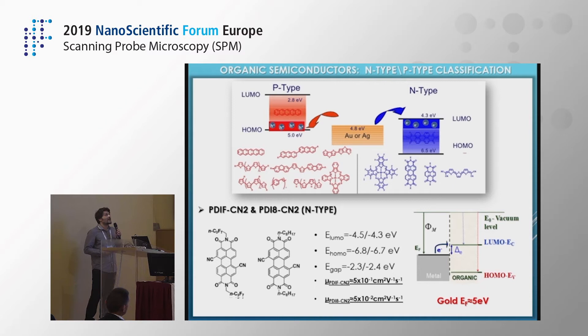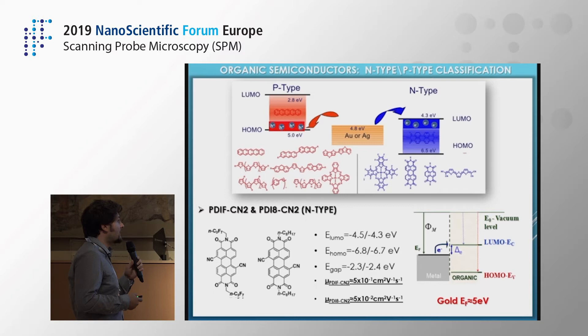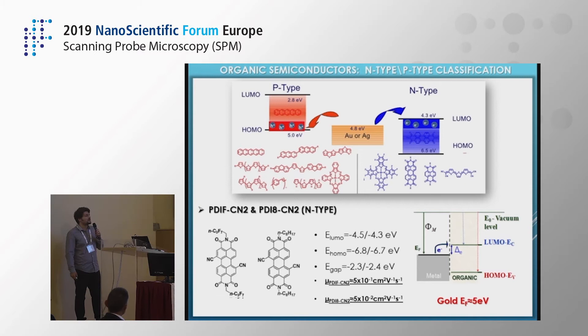The materials we focus on are called PDIF-CN2 and PDI8-CN2 — both perylene diimide derivatives with electron-withdrawing CN groups on the side that lower the LUMO levels, in order for electrons to be easily injected from gold, which is the most widely used electrode material for this kind of organic device.